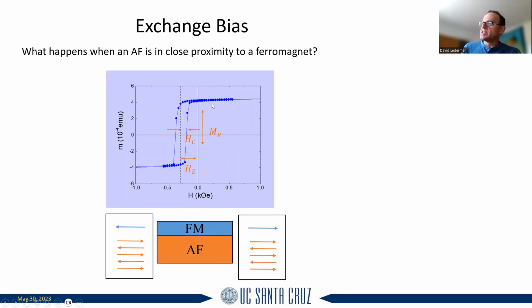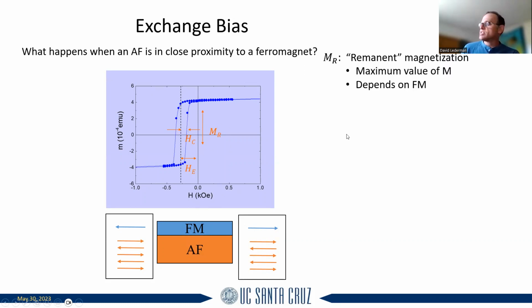In many cases, what you see is something like this. Here's your hysteresis loop. But now look, the important thing is that the externally applied field is actually over here at 0. And then you can see that the hysteresis loop has shifted away from the 0 external field line. So it's not like I showed you before, where it was symmetric about H equal to 0. Here, the entire thing has shifted to the left. So it's as if you had an external field in one direction that you're not reversing at all. So everything gets moved to the left. And then the question is, why does this happen?